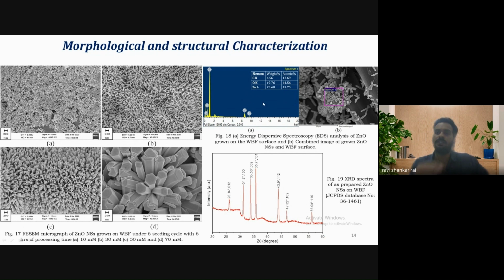After that, we analyzed it with the help of energy dispersive spectroscopy, and it was found that there is an enormous amount of zinc and oxygen present on the surface, and no foreign element was seen. After that, the peaks of the structures were seen with the help of XRD spectra, and it was found that a hexagonal nanostructure has developed with high intensity peaks, and the entire data has been verified with the JCPDS database number 36-1461.